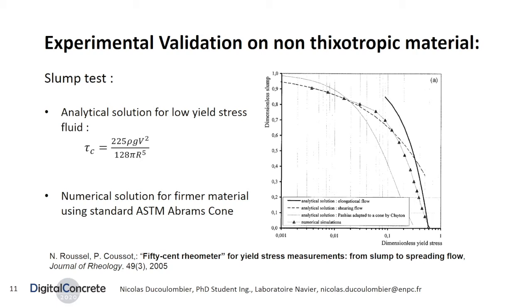the traditional slump test. For some experiments, the slump test is performed using a 280 cubic centimeters cone filled with the material just after mixing, approximately 10 minutes before the slug test, and the estimation is made using the asymptotic solution provided by Roussel and Coussot. For other experiments, the standard 6-liter Abrams cone is placed under the printing head and filled with the extruded material. Slump yield stress is then estimated using the numerical solution also provided by Roussel and Coussot.